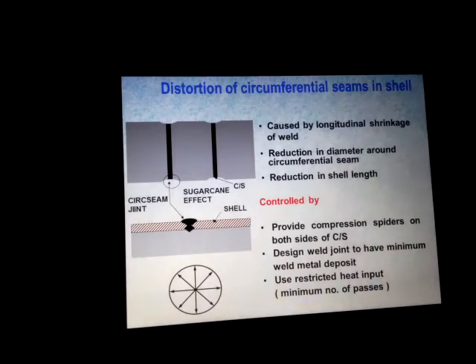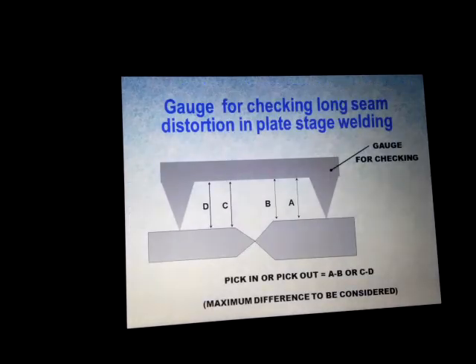Distortion of circumferential seams in shell, is caused by longitudinal shrinkage of the weld, producing reduction in diameter around the circumferential seam and reduction in shell length. It is controlled by providing a compression spider on both sides of C/S. Design the weld joint to have minimum weld metal deposit. Use restricted heat input and a minimum number of passes.